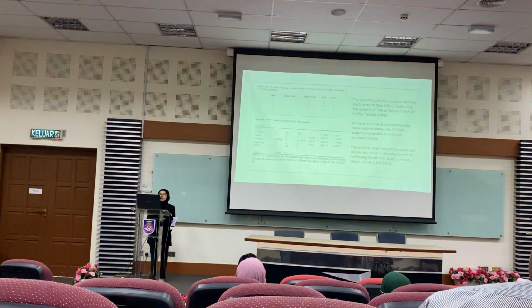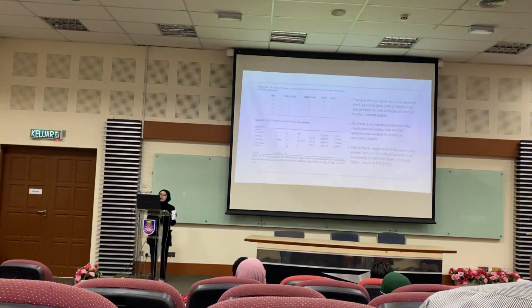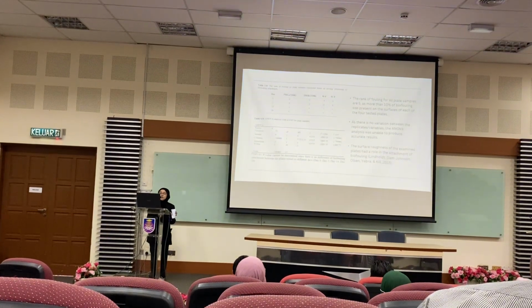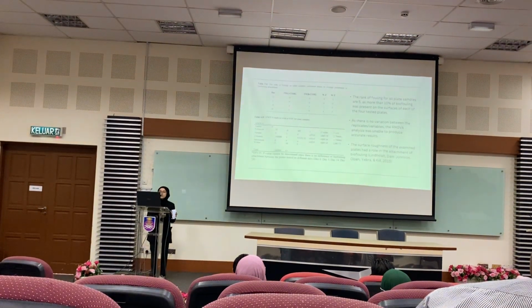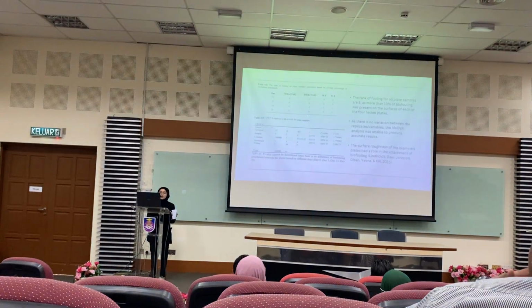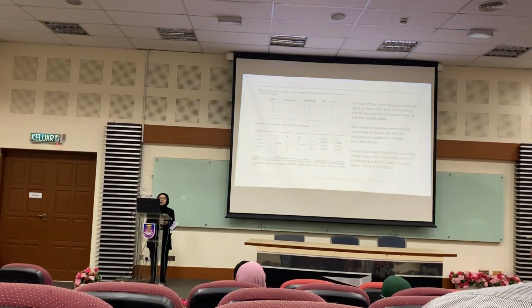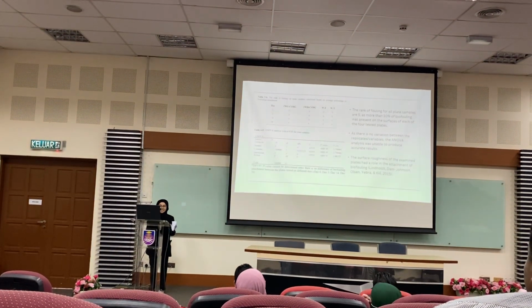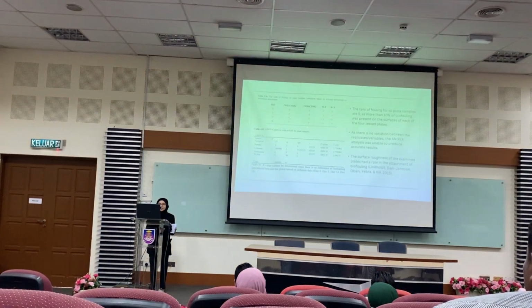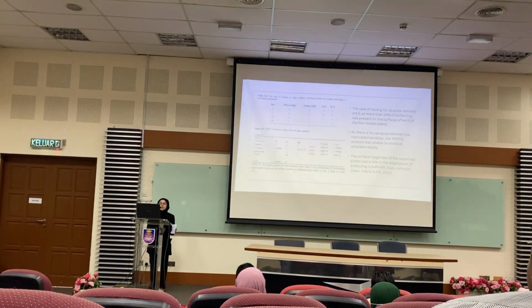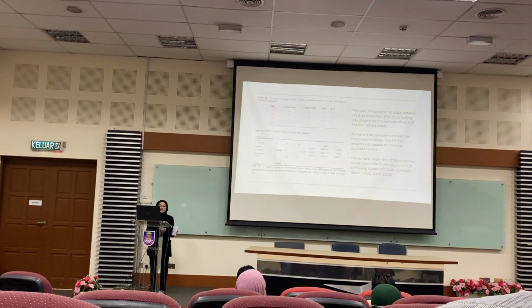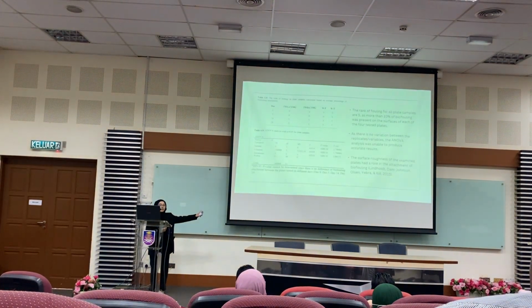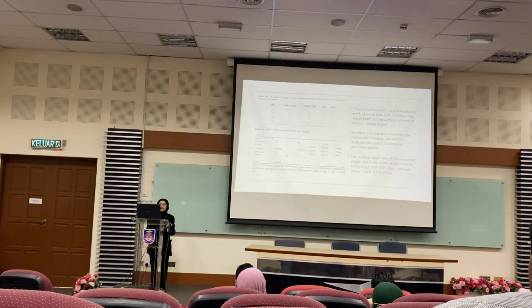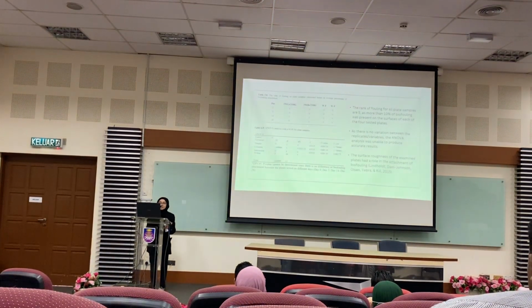The rank of fouling from day 14 until day 28 is 5 because more than 10% of the surface had the presence of biofouling. As there is no variation between the plate samples, the ANOVA was unable to produce accurate results. As you can see from the array there, the p-value cannot be determined since there is no difference of biofouling attachment between the plates tested.